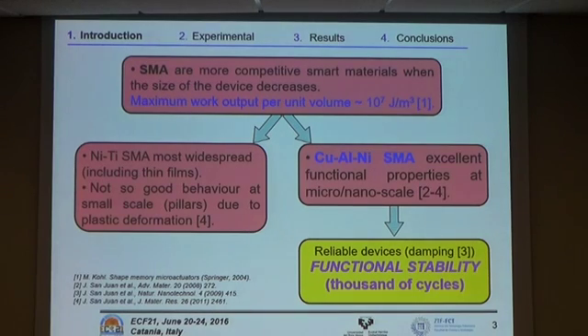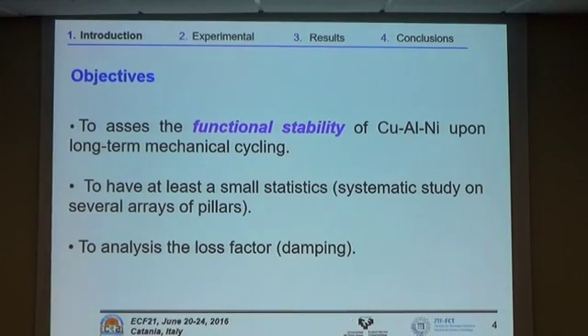And of course, if one wants to use this material in a real application, one has to look for the functional stability of these materials, for example, in damping application, but you have to go more than 1,000 cycles. Of course, this in comparison with fatigue studies is not too much, but at least it will be a starting point. So the idea was to study the functional stability of copper-aluminum-nickel upon long-term mechanical cycling, to have at least small statistics about these properties.